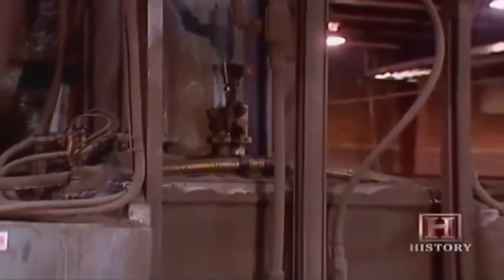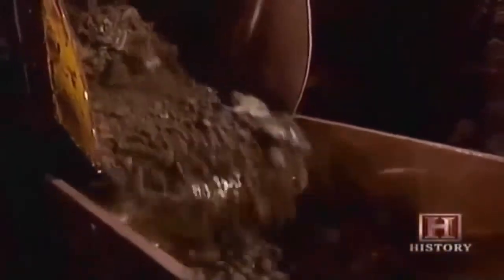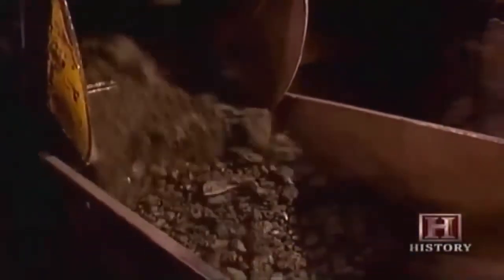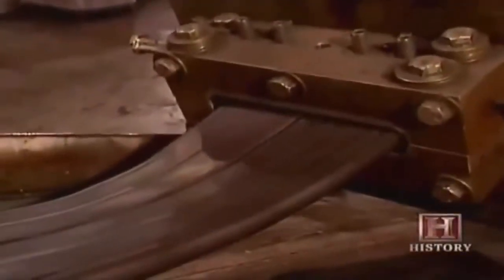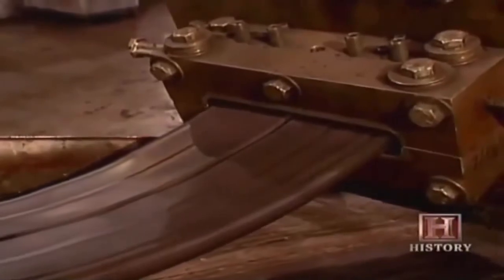We use rotors to distribute the material evenly, and then there's a large ram that puts pressure on the mix as it is mixing. Between those two, we get an even distribution, and we readily mix the ferrite throughout the rubber. It takes approximately 5 to 7 minutes to run a batch. Once the material is discharged from the intensive mixer, it's not in a format that we can use, so we dump it into what we call a batch extruder. We maintain the temperature of about 275 degrees through this process in order to keep the material able to extrude it easily.